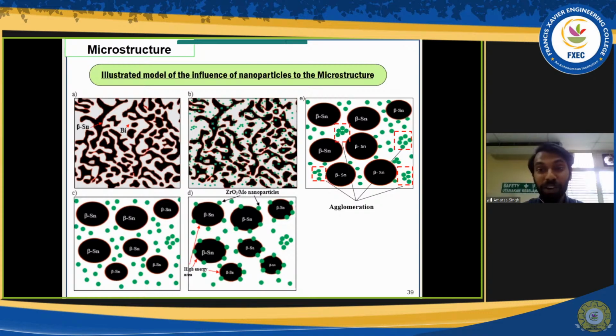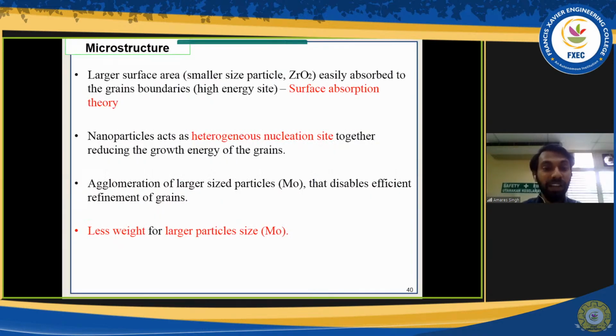Upon addition of nanoparticles, the reduction is basically due to the nanoparticles of zirconia and 1% and 3% of molybdenum, because these nanoparticles restrict the growth of the β-Sn. So they produce a smaller or refined β-Sn area. But for the 2% additions, there was agglomeration and there was not much presence of molybdenum, so there is no refinement process there.